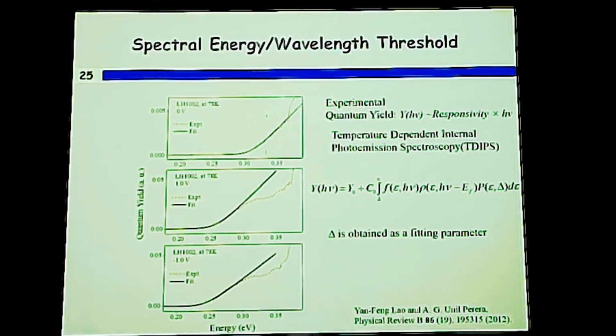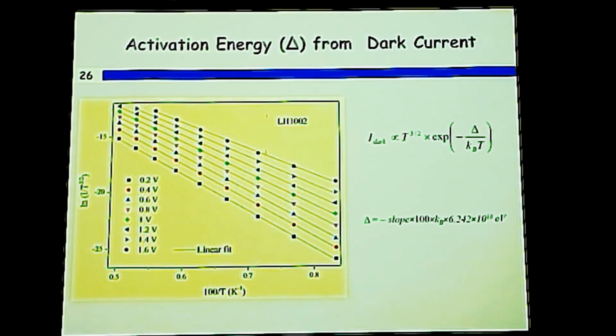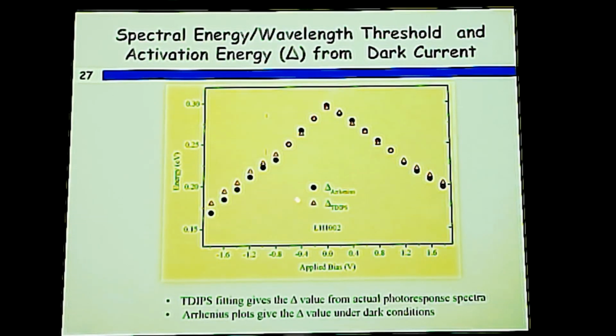There is another way to find that delta under dark condition, from the dark current. Dark current is proportional to this term, and if we plot the natural log of the dark current divided by this temperature term versus inverse of temperature, then we get this kind of plot, and from the slope of these plots, we can get the activation energy under the dark condition. So these are the values. We see in negative bias there is some difference at high biases, again probably because of that unintended small gradient that is there.